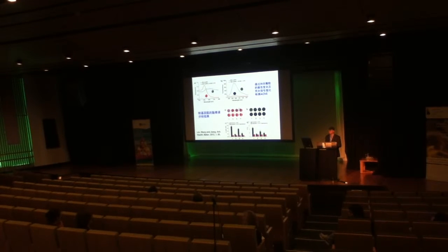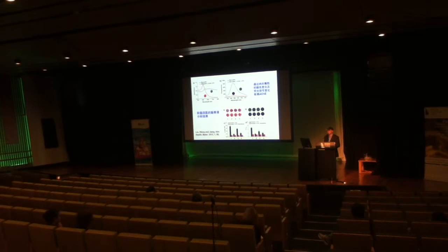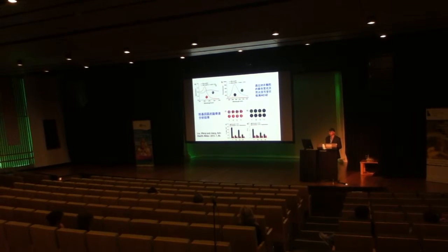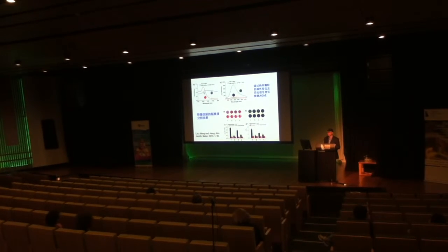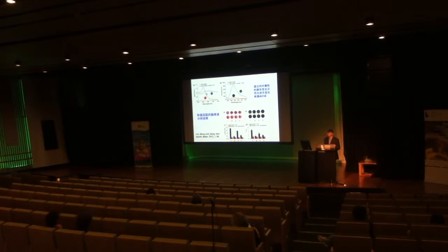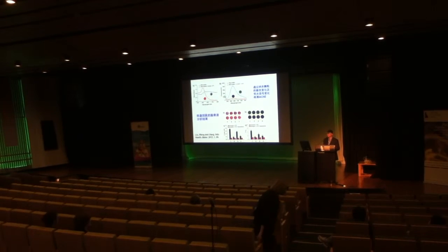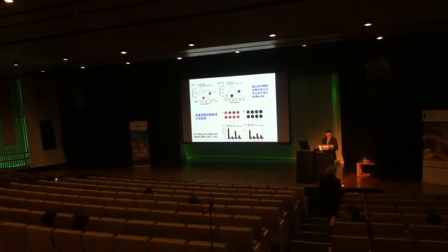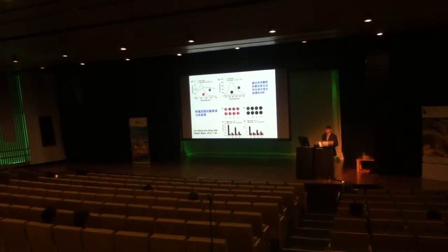So as I explained to you just now, if we have this rhodamine-labeled gold nanoparticles and add the enzyme and the substrate, what you'll see is that the color, the absorbance will change. At the same time, the fluorescence will also change. This sort of acts as a dual readout for the presence of the acetylcholinesterase in the diagnosis of Alzheimer's disease.